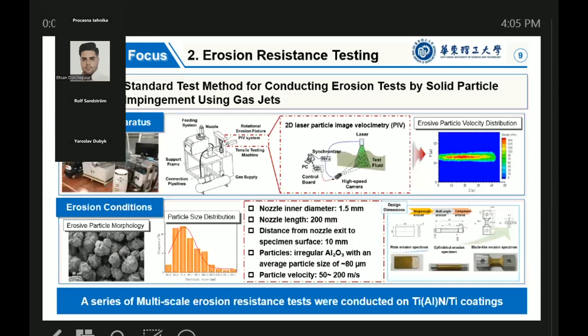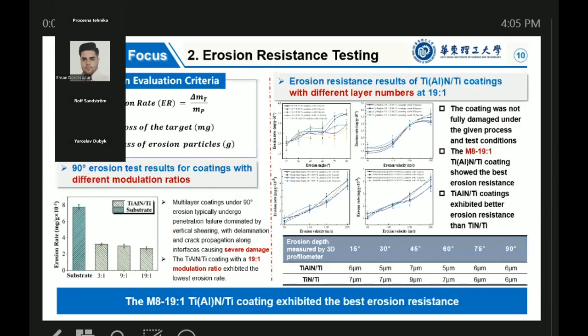Next, we evaluate the coating erosion performance. We built an erosion test system following the standard, using irregular alumina (Al2O3) particles at various velocities and impact angles to simulate real erosion conditions, providing a comprehensive assessment of the coating performance. The erosion rate, defined as the mass loss per unit eroded mass, was used as the evaluation index, and at